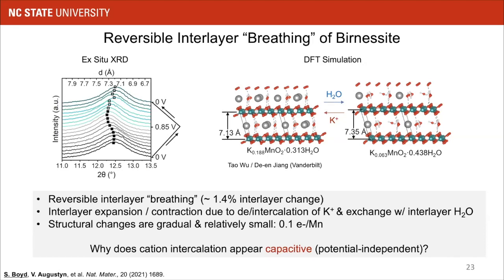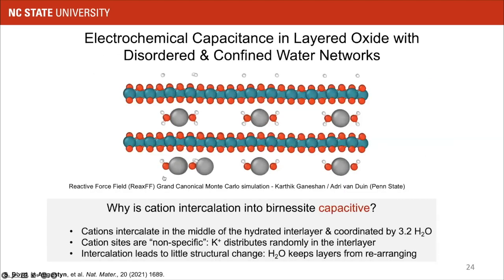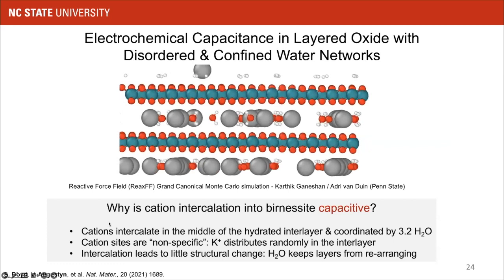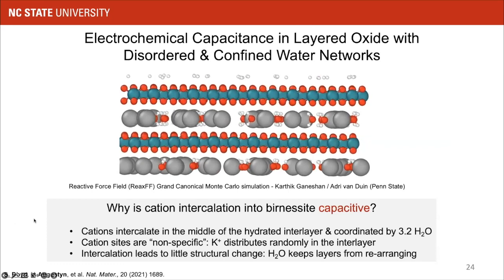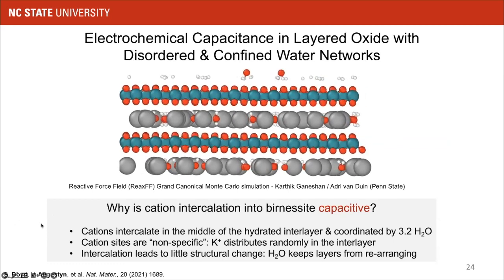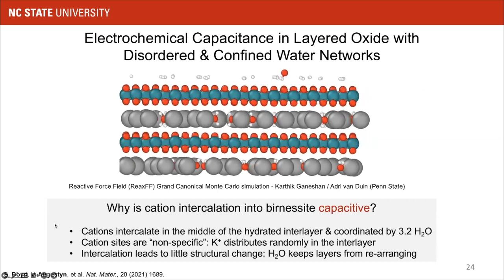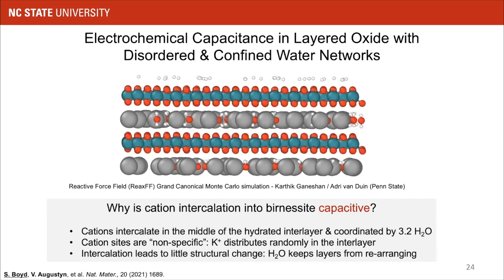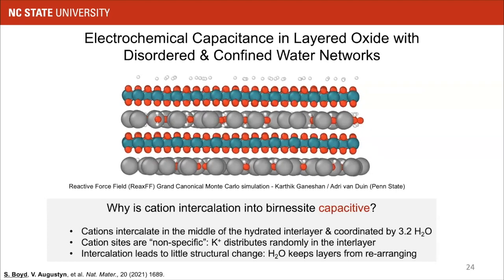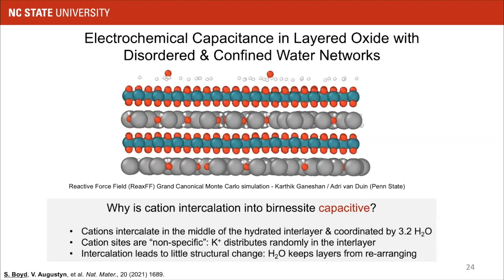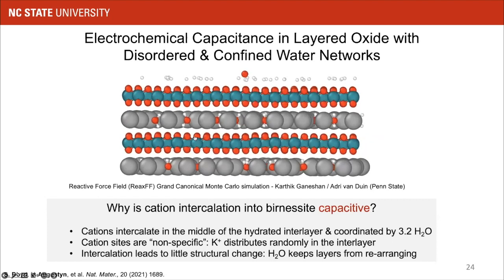So the question was, why does this cation intercalation appear capacitive or potential independent, whereas most cation intercalation does have a very specific potential dependence, which is what we observe in batteries. So our hypothesis is that this has to do with the presence of those confined water molecules. These are reactive force field grand canonical Monte Carlo simulations by our collaborators at Penn State. We understand this material as basically being very much dependent upon the nature of this interlayer environment.